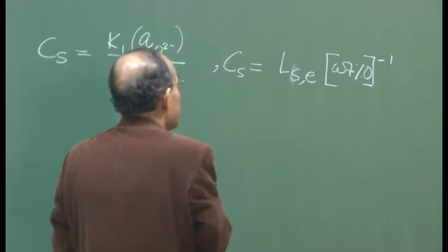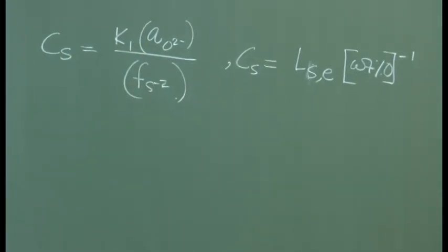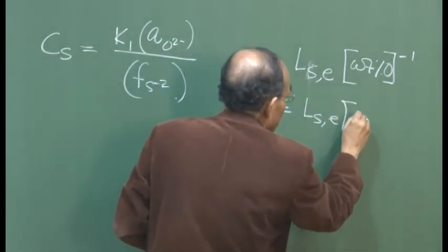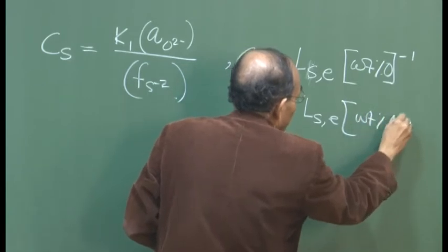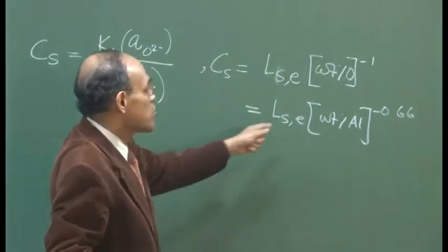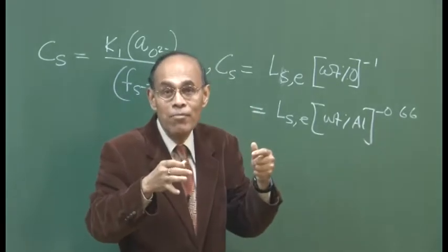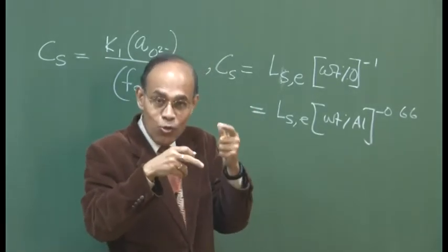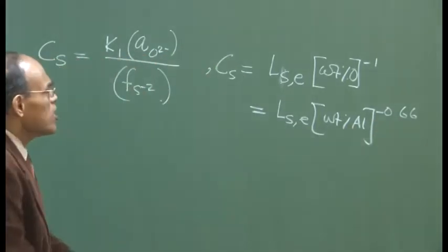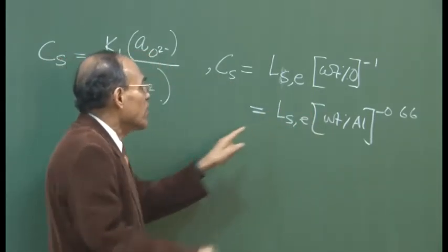Okay. So, which essentially tells us that one can also write this in terms of an aluminum killed steel, for example, in terms of what percentage aluminum raised to the power minus 0.66. This comes from the figure 0.66, because if you think of oxygen aluminum equilibrium Al2O3, so 2:3 proportion oxygen is to aluminum, and that is how this has come into the picture. So, this is another definition of CS.